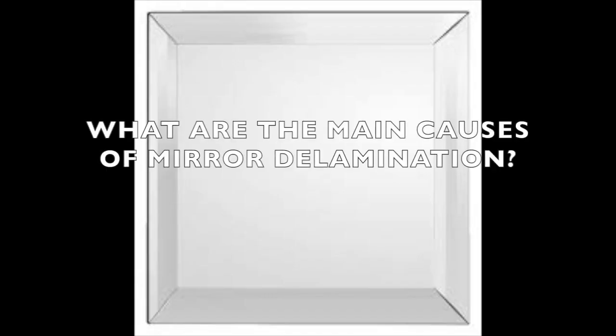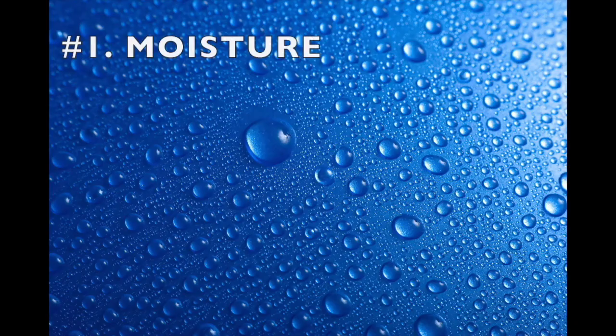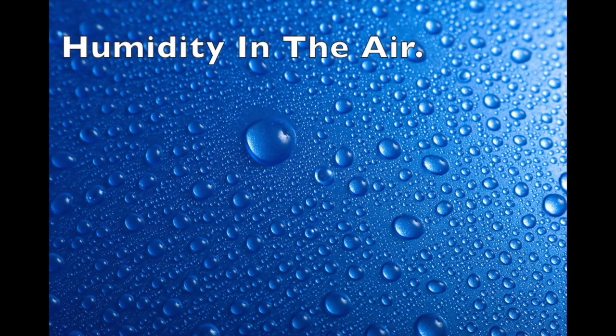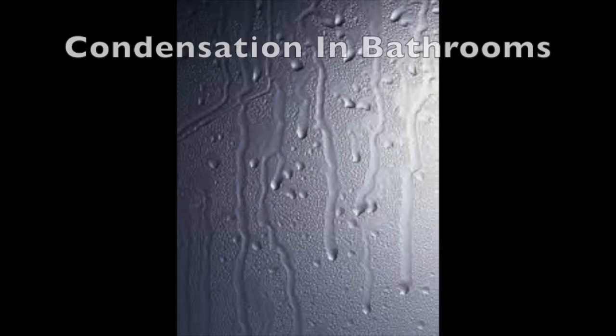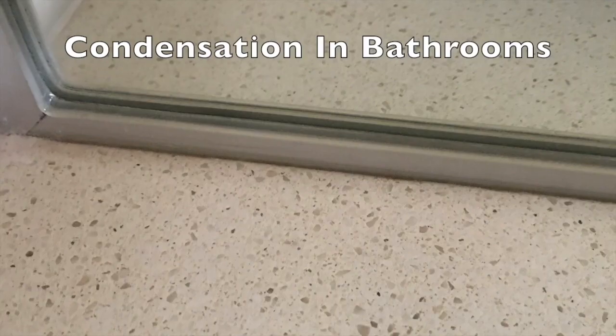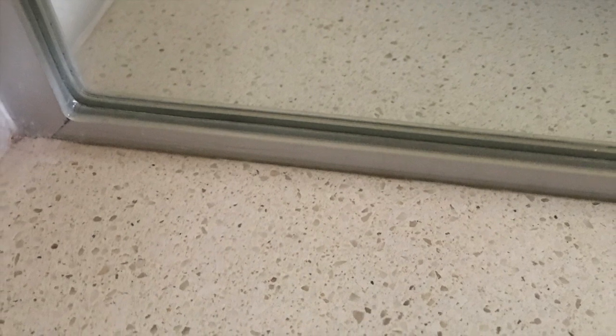So what are the main causes of mirror delamination? Moisture entering the exposed edge is a major factor in the delamination of a mirror. This moisture can be as a result of humidity in the air or is most likely from condensation in bathrooms. Mirrors in bathrooms are more susceptible to delamination as condensation builds on the surface and runs down the face of the glass into the frame.